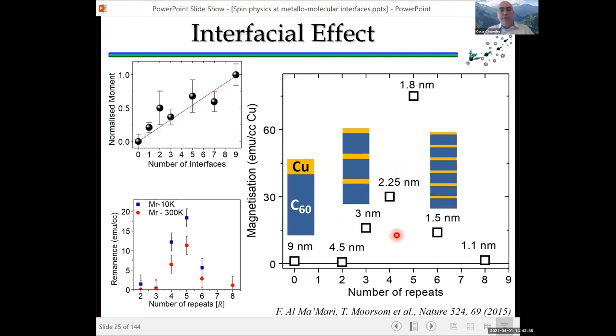So we always have 9 nanometers of copper, but when we split it into 8 repeats, so 1.1 nanometers, these continuous copper layers, there is no magnetization. If we split it into 2 repeats, so 4.5 nanometers of copper, then again, no magnetization. And the same thing if you just put 9 nanometers of copper on top of the system.